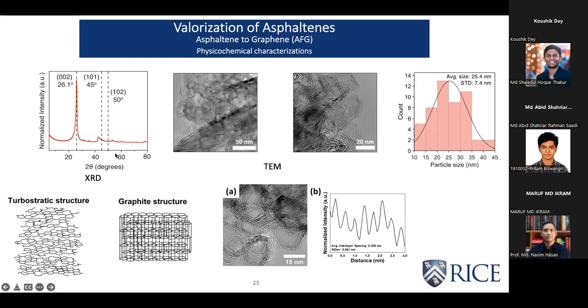Going back to XRD, in literature, we found that when the peaks at these dotted lines reduce, that's another signature of turbostratic structure formation. So from these experiments, we deduce that what we have formed after the flash Joule heating process is a turbostratic structure, and this is important, why I will show soon.